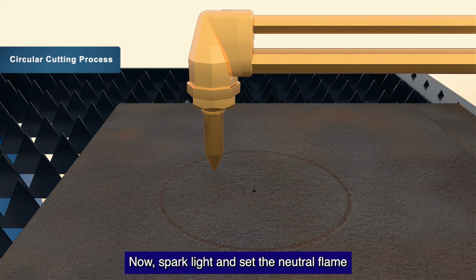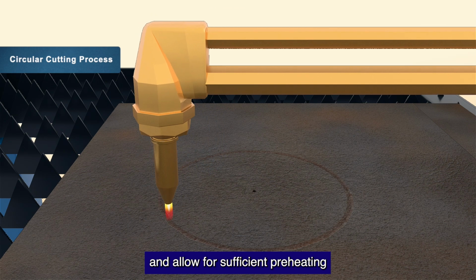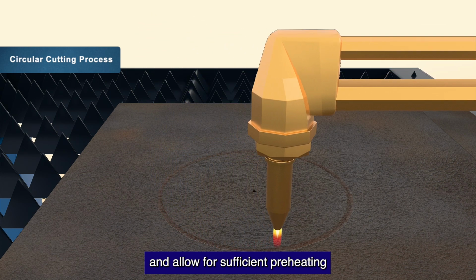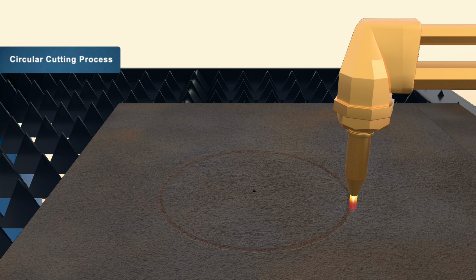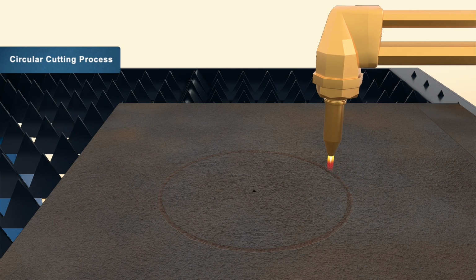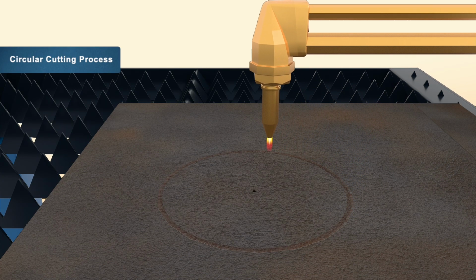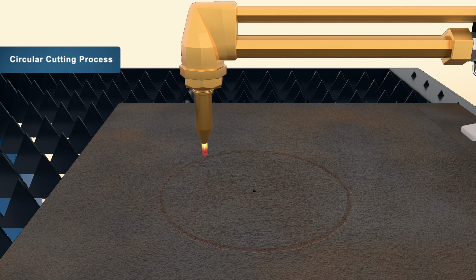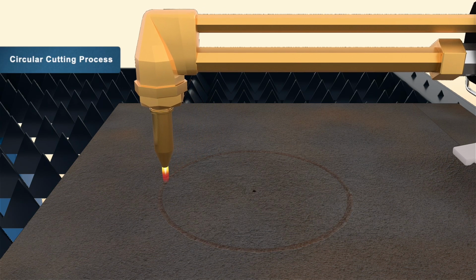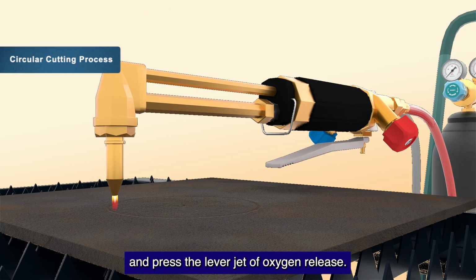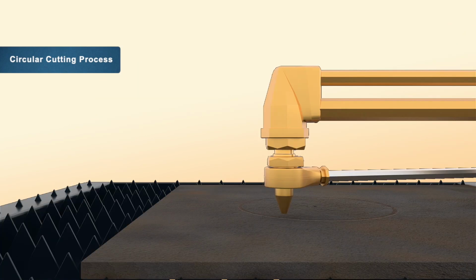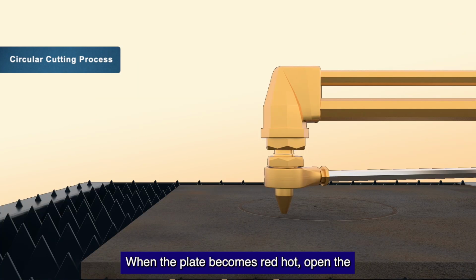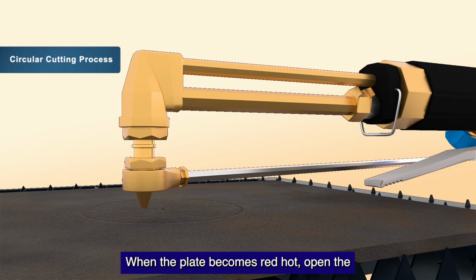Now, spark light and set the neutral flame and allow for sufficient preheating. And press the lever to release the jet of oxygen. When the plate becomes red hot, open the stream of cutting oxygen and cut the circle.